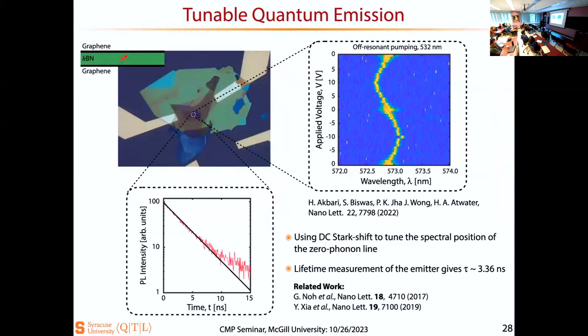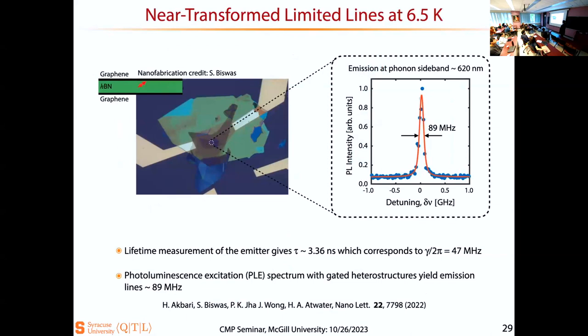And then this is the experiment which I talked about, in which I'm just showing the result. We fabricated our device using still the exfoliated boron nitride, but now it is gated by two graphene layers. Using the Stark effect, we were able to get rid of local charges, but also able to tune it. And using Stark tuning, we clearly saw a linear scaling of the shift in the resonance. Not only that, we also observed an absorption line close to 89 megahertz, which is within a factor of two close to the lifetime limit. So what do I learn from that?